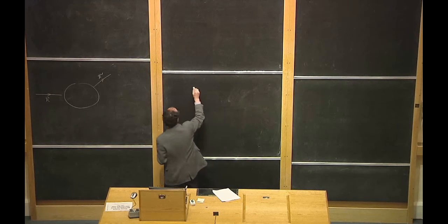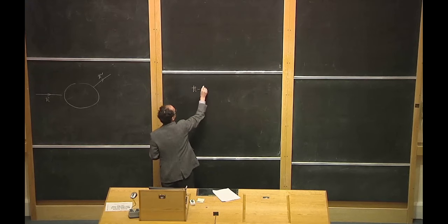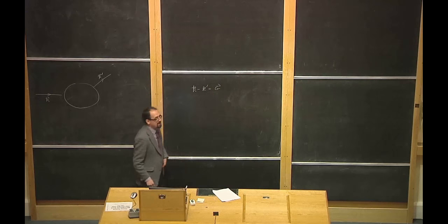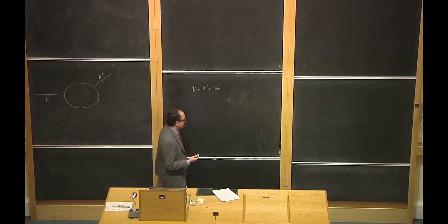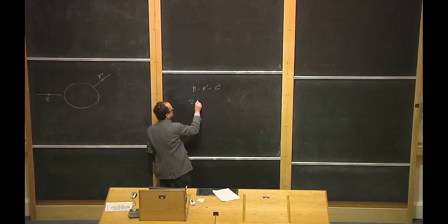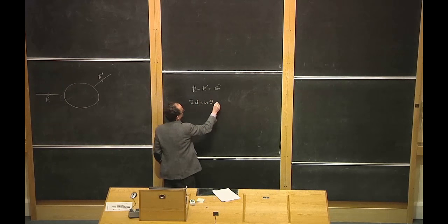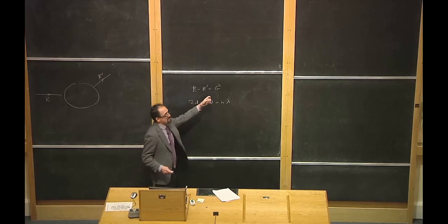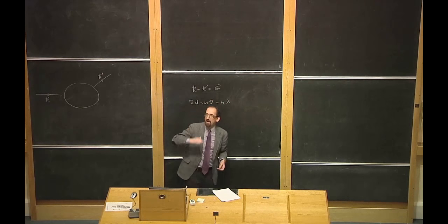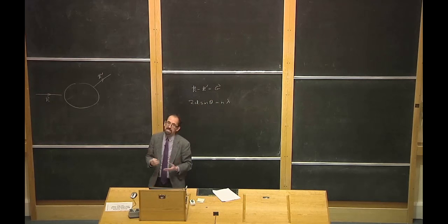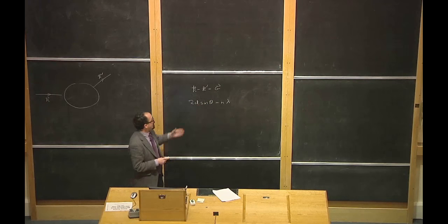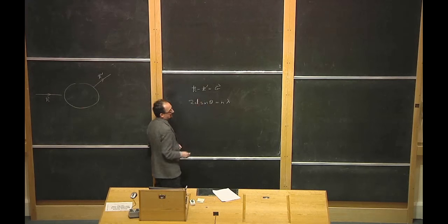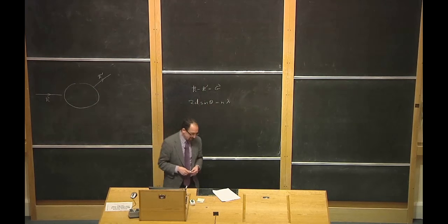First of all, in order to get scattering from k to k prime, you must have k minus k prime equal a reciprocal lattice vector G. And we derived in the last lecture that that's equivalent to the Bragg condition, 2d sine theta equals n lambda. In other words, since a reciprocal lattice vector is orthogonal to a family of lattice planes, what you're actually getting is diffraction off a diffraction grating with lattice plane spacing d orthogonal to that vector G.